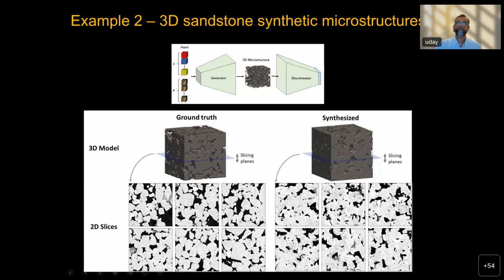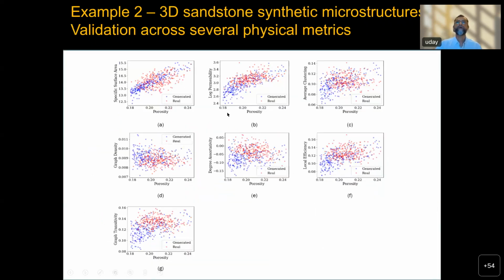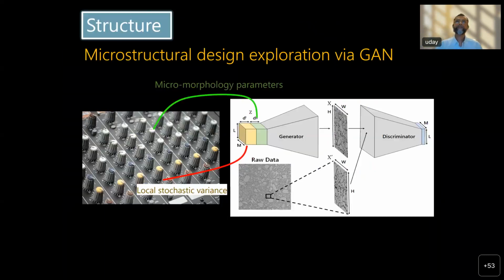And these are showing 2D slices of these microstructures and quantitative comparisons. This is very dense. I won't go into it, but you can look at various metrics of the quantitative characteristics of the real microstructure and the synthesized, and we show that the synthesized microstructures capture the characteristics of the real microstructures fairly well. So that's the structure generation part.